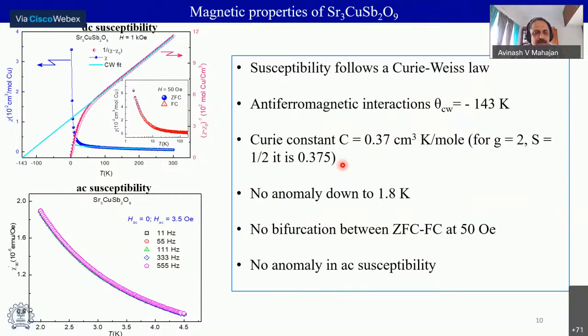Okay, we measured the bulk properties. Here I'll just present a subset of that. So, theorists told us to look for Curie-Weiss behavior. So here is susceptibility as a function of temperature. And indeed, at high temperature, it fits well to a Curie-Weiss behavior with a negative theta, about 140 K. The Curie constant is good for a typical spin-half system.